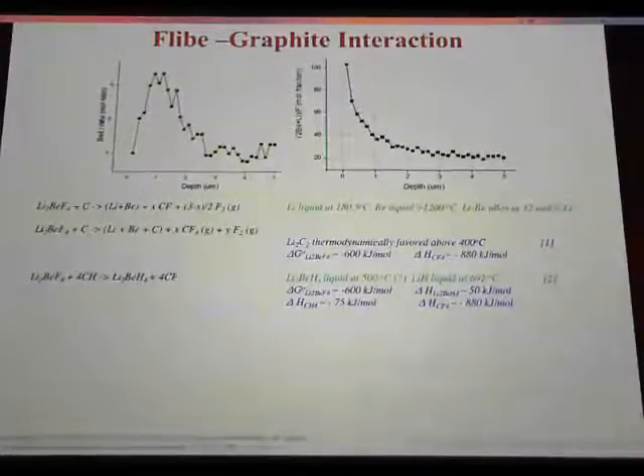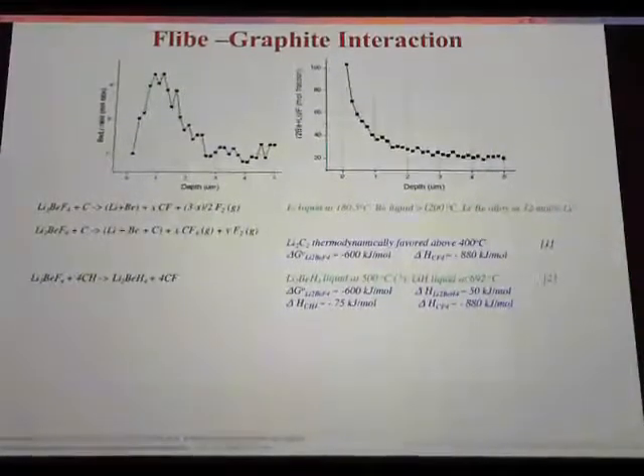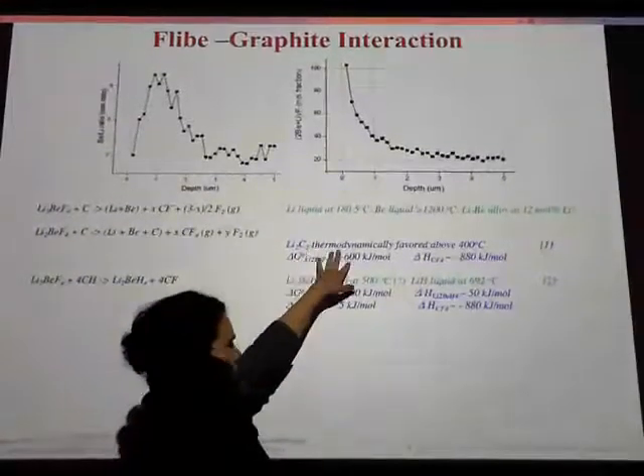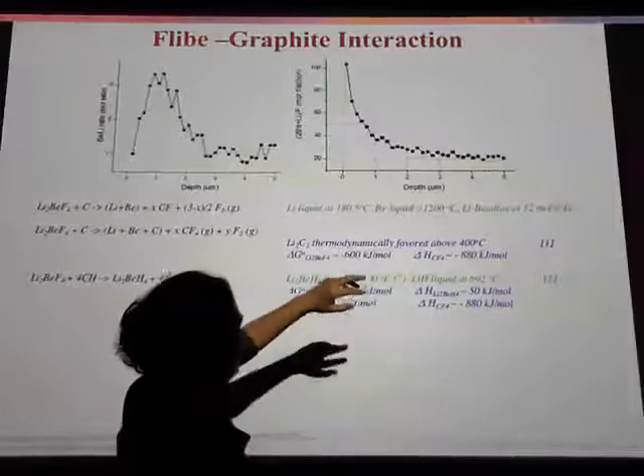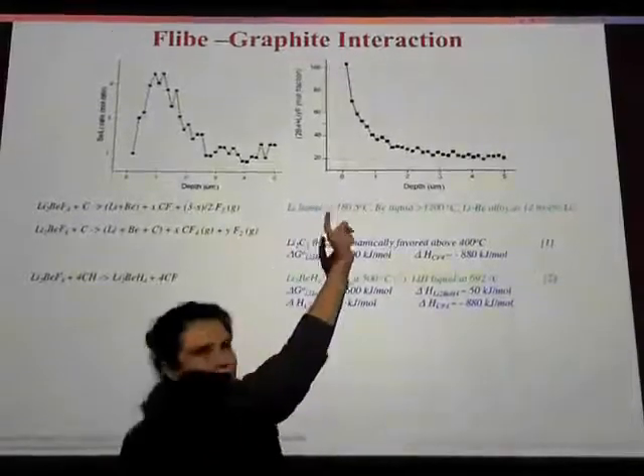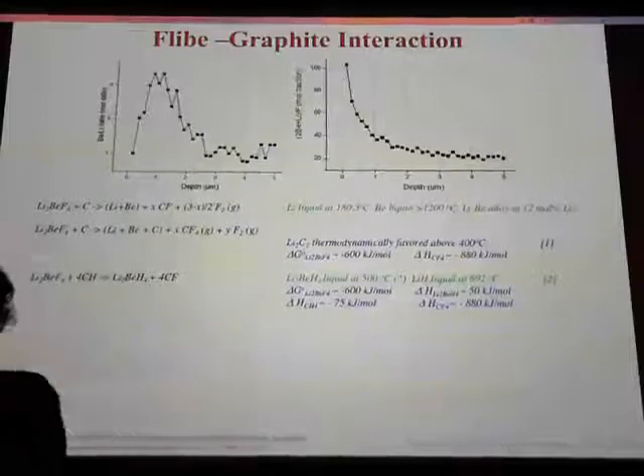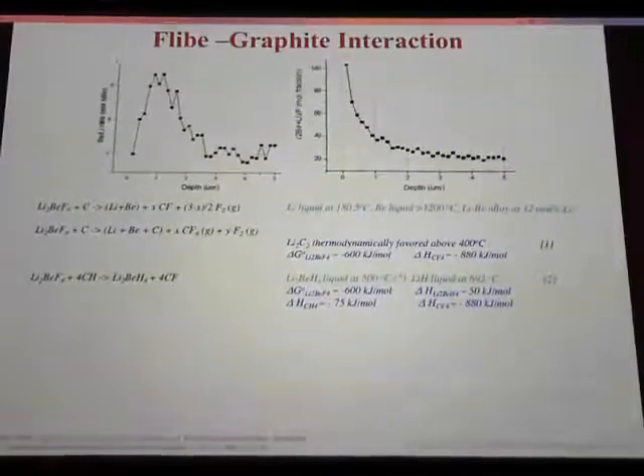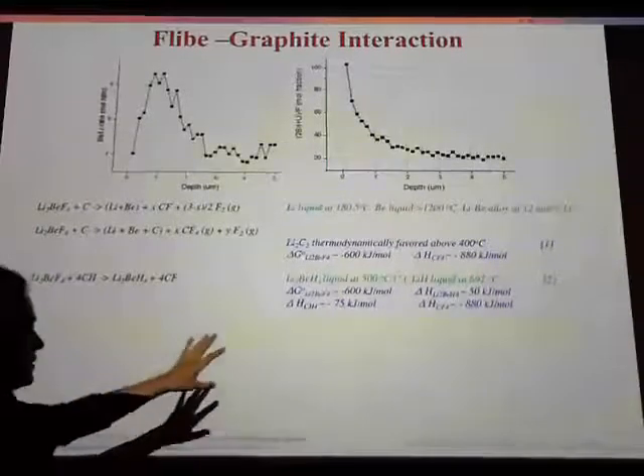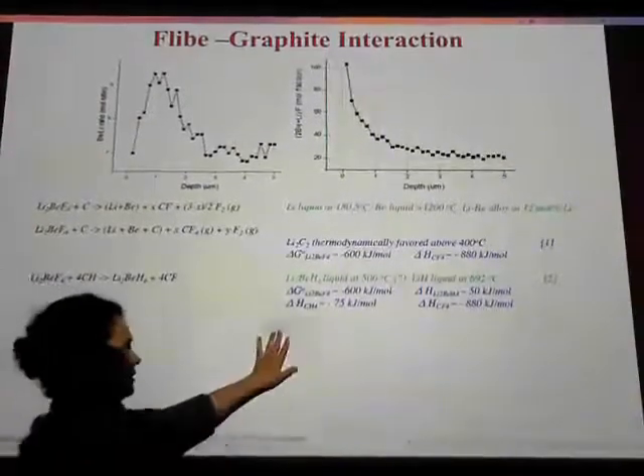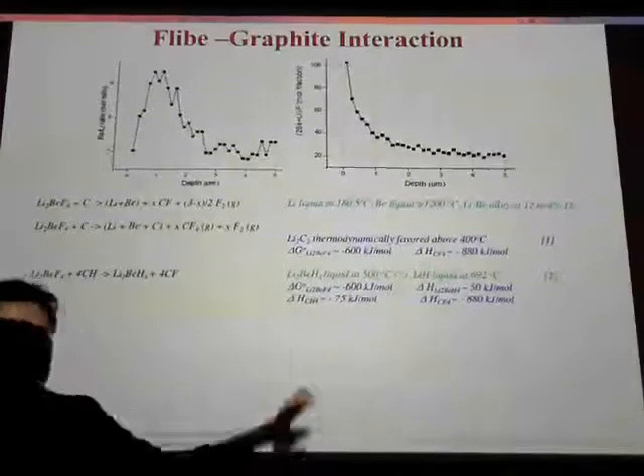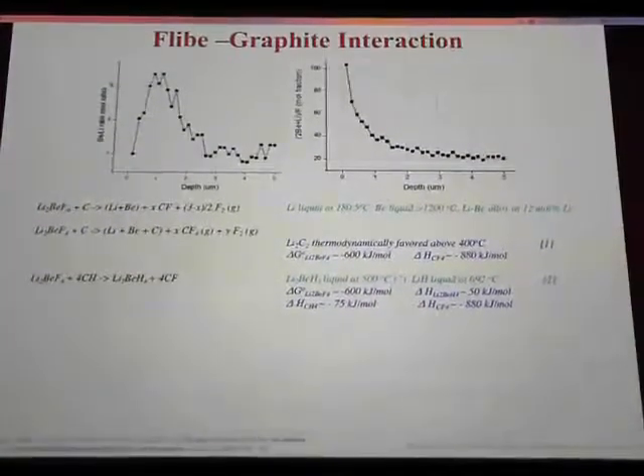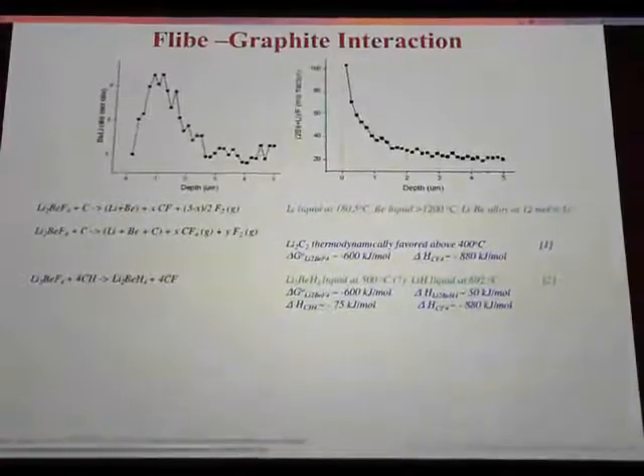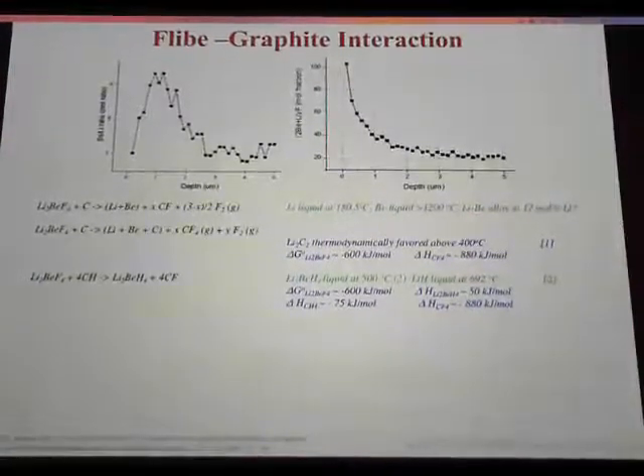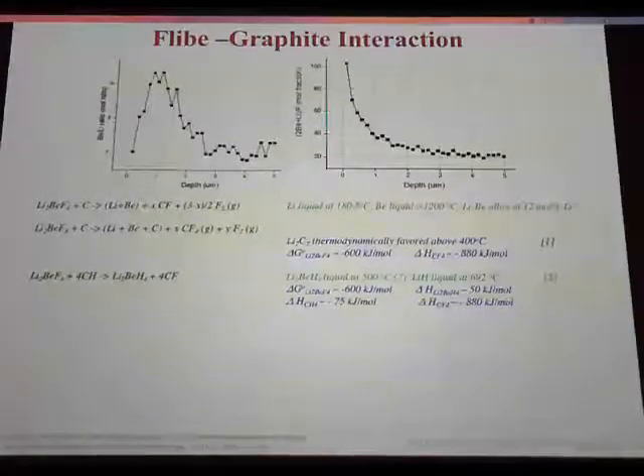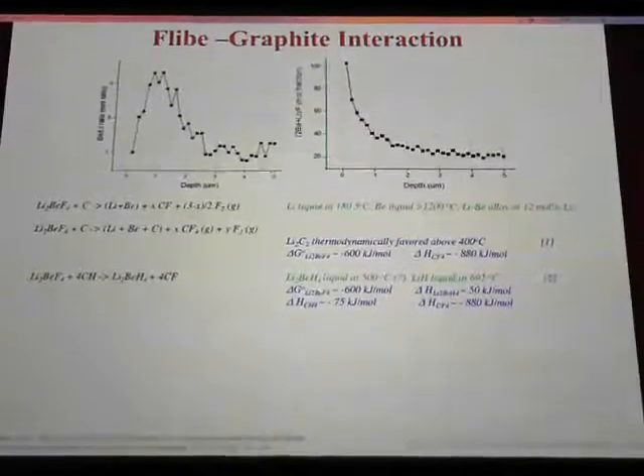So these are some of the things that might be happening. There's some data on the fact that lithium carbide is thermodynamically favored at 400 Celsius. To keep in mind is that lithium is liquid at 180, so we might be forming liquid droplets of lithium that then freeze? I don't know. It's puzzling. I just got this data yesterday, so I apologize if the analysis is not complete, but it's puzzling. And we should figure out what's happening, because it would definitely affect tritium absorption. If you have metal, then tritium will form hydrides, so that's going to be different than tritium forming chemical bonds on graphite. So we need to figure that out.